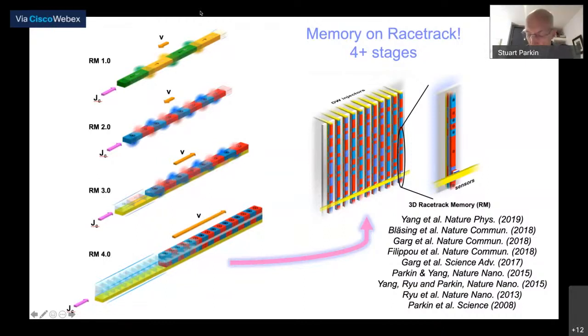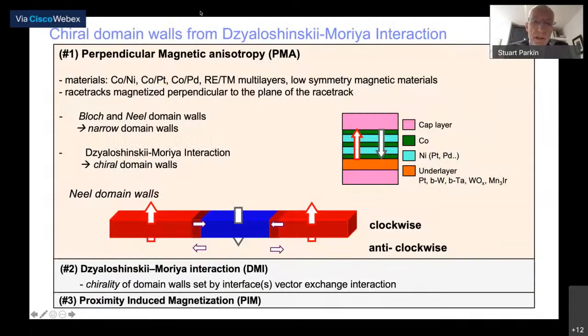Well, here's some references if you're interested in the details of the physics behind racetrack, but I want to just mention a couple of points. One is that the racetrack devices today involve engineering of atomically thin magnetic layers. On the one hand, we want the magnetization within the racetrack not to be parallel to the racetrack, but to be perpendicular. This enables us to make narrower magnetic domain walls. When we do this by, for example, making ultra-thin layers of cobalt and nickel, each layer is just 1 to 3 angstroms thick. We can make this by conventional sputtering techniques. These form very beautiful, perpendicularly magnetized domains.